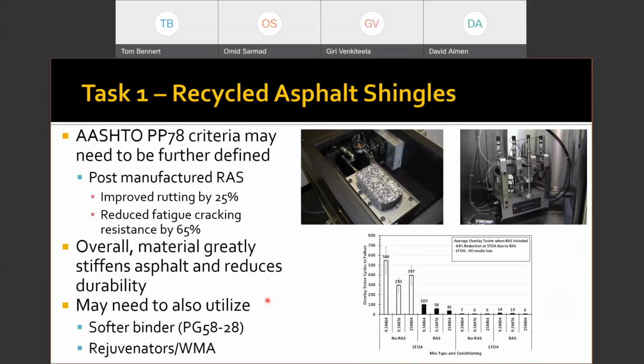Now, that doesn't mean that these products still can't be used, but you're going to have to significantly modify the way that we currently treat our asphalt mixes by using what we call rejuvenators, using some sort of a chemical package to soften the asphalt binder in the shingles. Again, looking at a softer asphalt binder. And mind you, this is really only for the manufactured waste. So this is only for the waste product that comes from the factories. Currently, the New Jersey DOT does not allow post-consumer or tear-offs, old shingles from housing, because of the possible asbestos that might be in there.